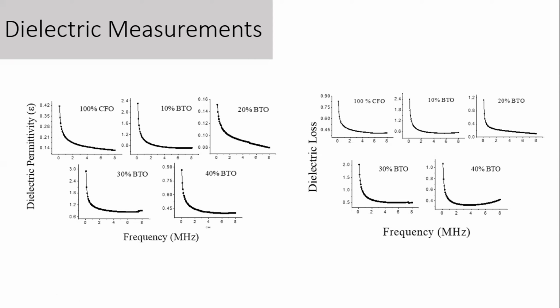Now, a uniform trend was not obtained, and what we could deduce from that is that in these nanocomposites, we have the role of two composites playing here. So with the cobalt ferrite, we have barium titanate and silicon carbide. So here, when one part is playing a major role, the other part is inhibiting its role. And the trend, as we are increasing the percentage, is reversing. So that was the idea we used, and we tried to understand why we are getting the data like that.